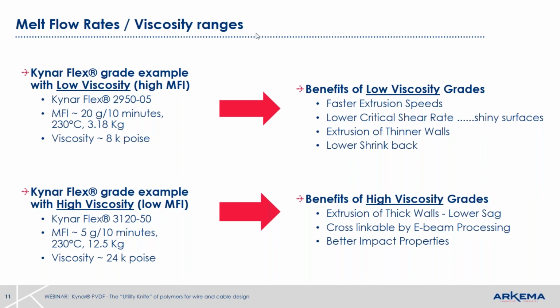Let's talk a little bit about viscosity and melt flow rate. As you can see here, we have some low viscosity grades like Kynar Flex 2950-05. And you can see its viscosity is 8, melt flow rate is around 20 with a 3.18 kilogram load. One of the benefits of a low viscosity material is this enables you to extrude faster. So a faster speed in production, lower shear rate. This lends itself to a shiny surface on your cable. You can also make thinner walls when you use a high melt flow rate material, and shrink back is dramatically reduced when you use this type of material. So low viscosity or high melt flow rate material will give you these attributes.